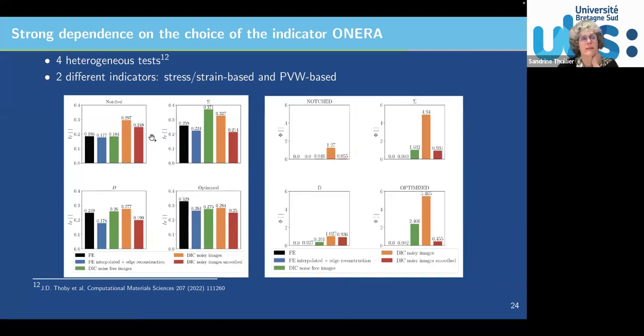Here are the results that these authors obtained, still at this research center. There is a lot of information, but each piece of information here is for one test: a notch one, sigma shape, D shape, and the optimized shape. And they compared the different colors. So let's focus on one test. They calculate the indicator, this one being the indicator based on strain and stress. They compare different configurations, especially the influence of the quality of the strain measure. Either you consider DIC without any noise, this is numerical simulation, but it was also possible to introduce some noise in the DIC.